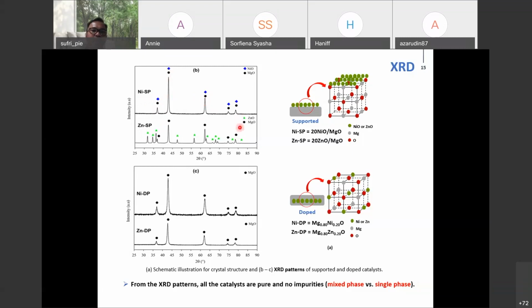However, this overlapping of the peaks does not occur for the zinc oxide supported on the magnesium oxide, because zinc oxide is hexagonal and magnesium oxide is cubic. So this is the indicator that the supported catalyst was obtained successfully. However, for the doped catalyst, as we see in the diagram, the active metal is inserted in the cubic structure. This is why nickel DP and zinc DP produce a similar XRD pattern. Again, this shows the doped catalyst was obtained. This is mixed phase. This is single phase.